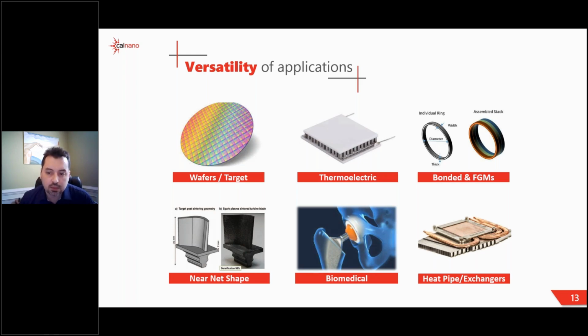Here's an example of dissimilar material bonding and some net shaping, which I'll get into more. But here's an example of a part that we sinter with 3 different materials that are all bonded together with no brazes, no welding, no melting, no other materials, with hermetic seal in between them. And we make it in a net shape as a ring, so we have no wasted materials in the inside or the outside, and that comes out as a final product in that form. And as I mentioned, sometimes these are made with powders between solids, sometimes they're multiple solids, and any combination in between.